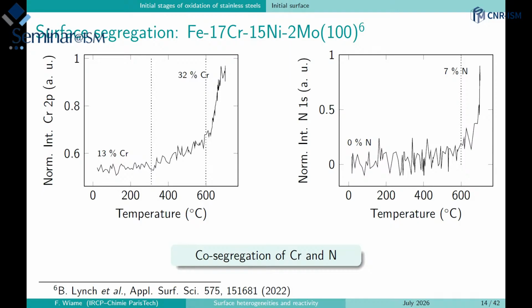And you can see that after 300 degrees Celsius, there is a first increase in the amount of chromium at the surface. Then after 600 degrees, you can see that the chromium is still increasing, and we can go from 13 to 32% of chromium. So really a change in the surface composition, which is quite significant.